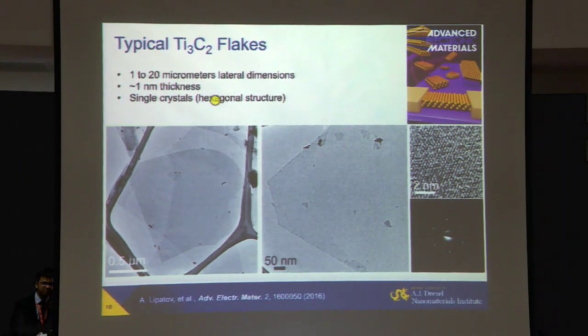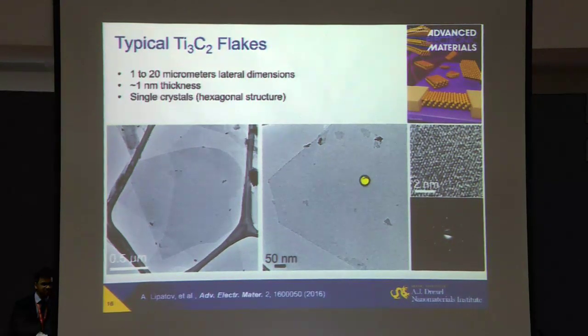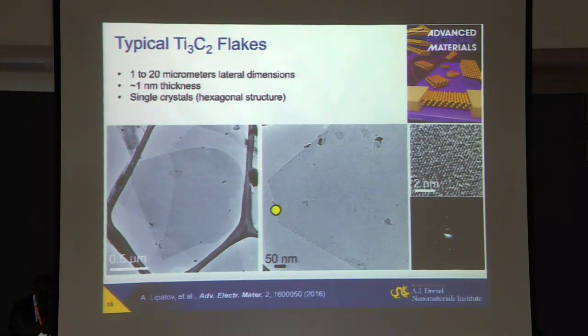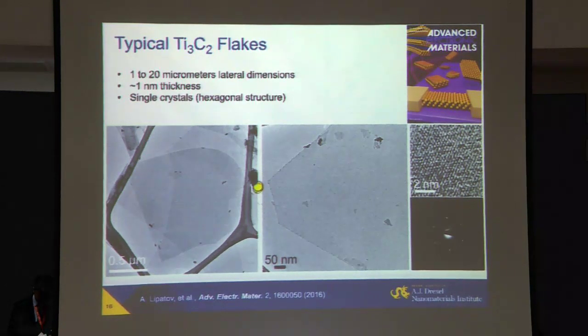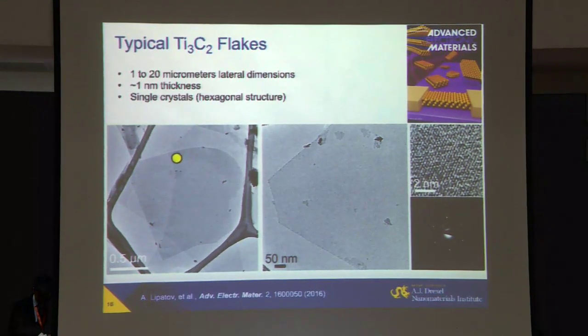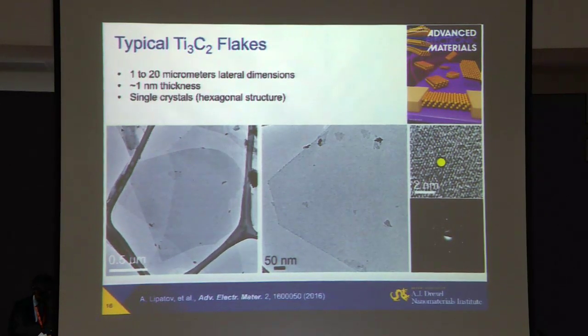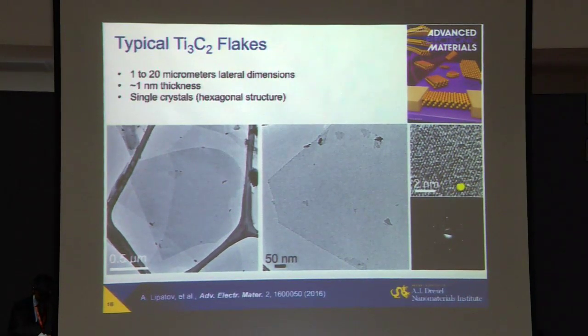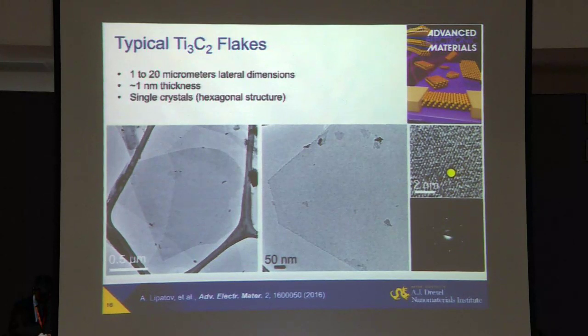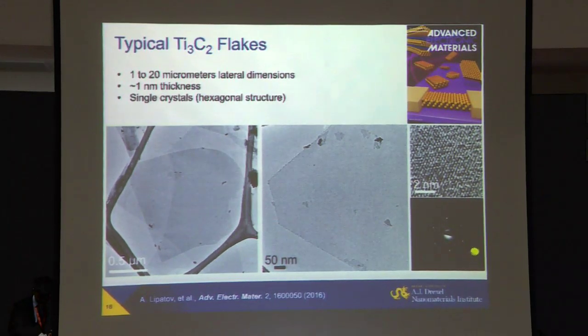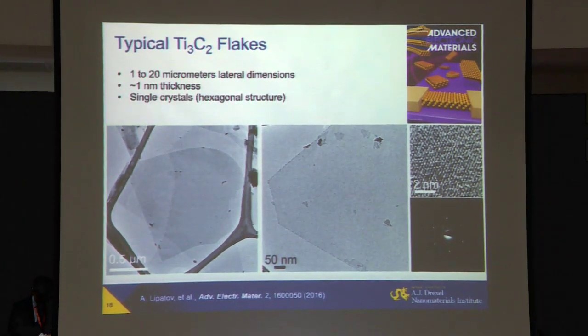But if you take a sophisticated, more expensive piece of equipment like an electron microscope and look inside, you will find flakes like this one, several microns in size, and this one follows actually hexagonal symmetry of the precursor phase, MAX phase, and those are monolayers of MXene laying here. Here a couple of layers are overlapping, and if you magnify it further, you will see that each of them has an ordered lattice, and they are single crystals, as this diffraction pattern shows. So we have flakes which are freestanding.